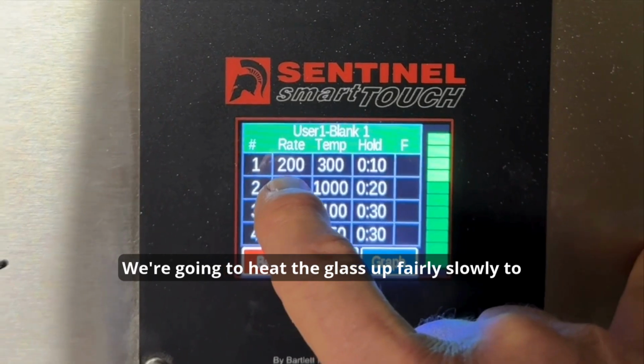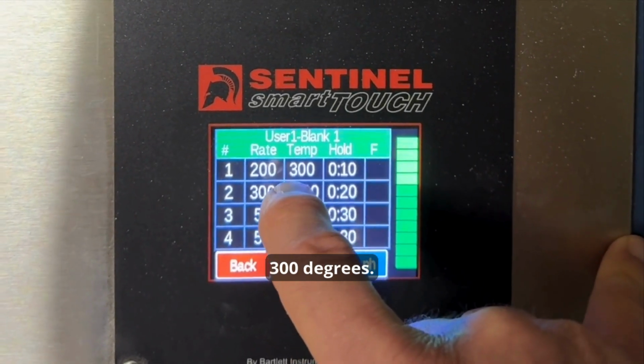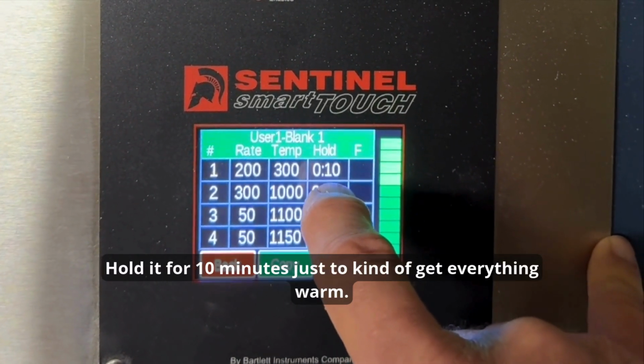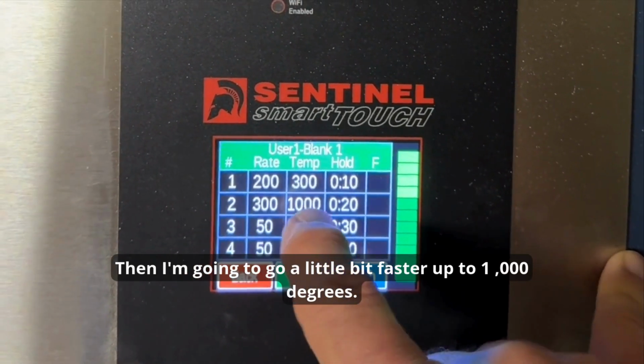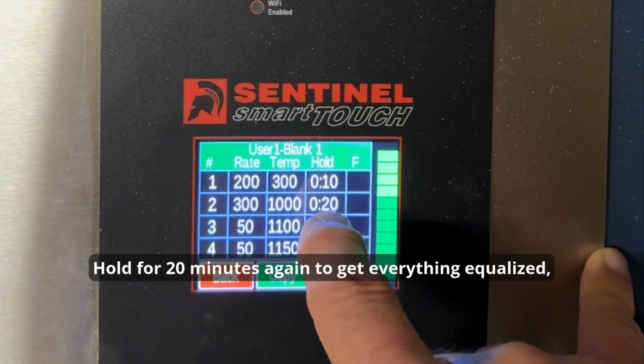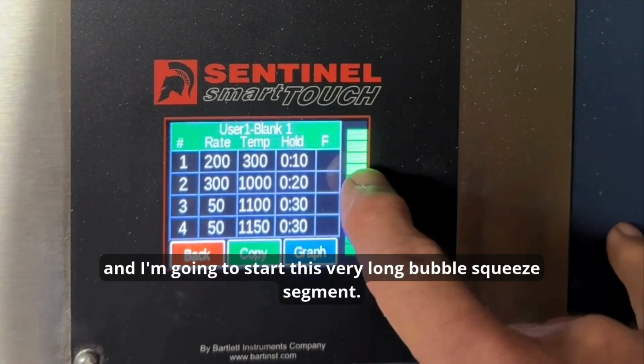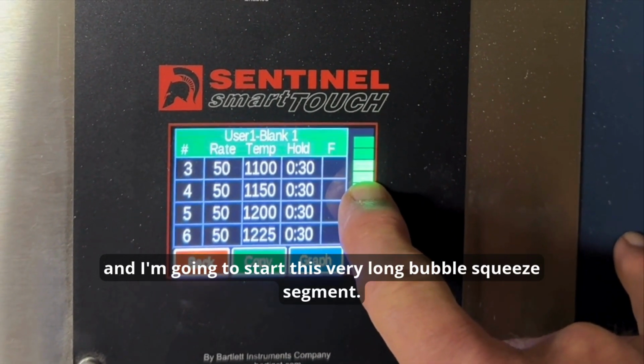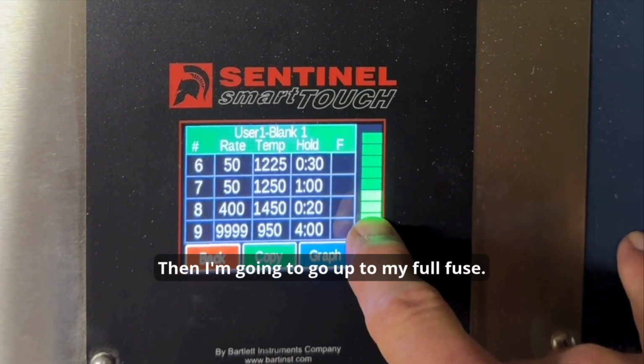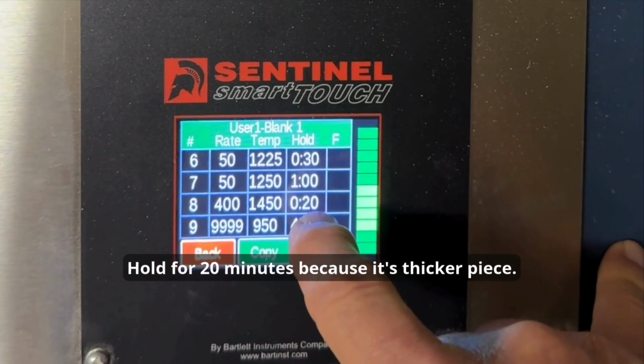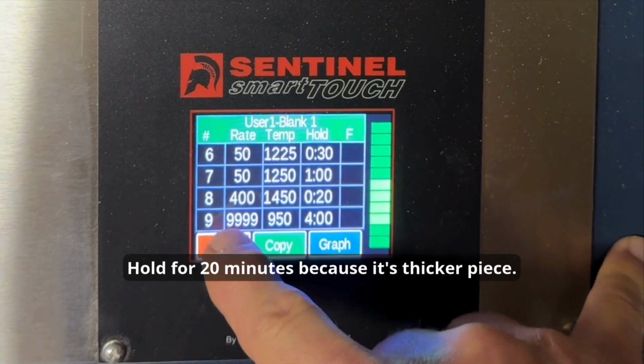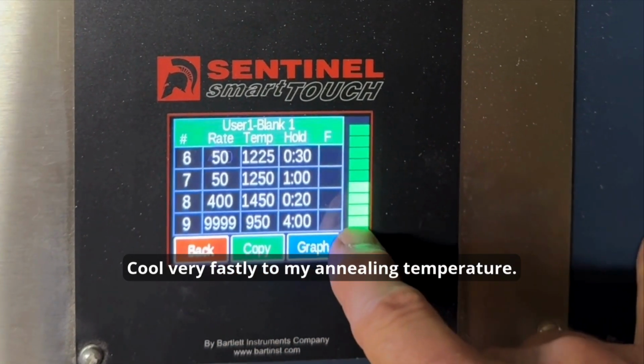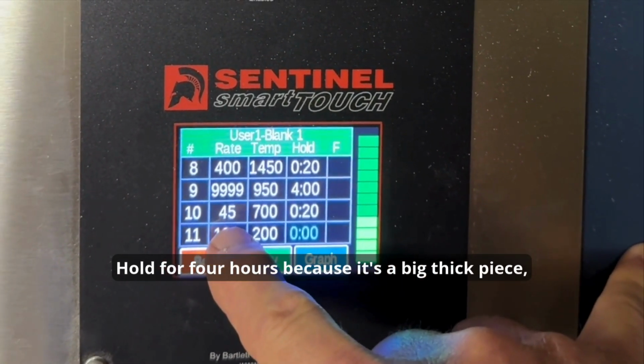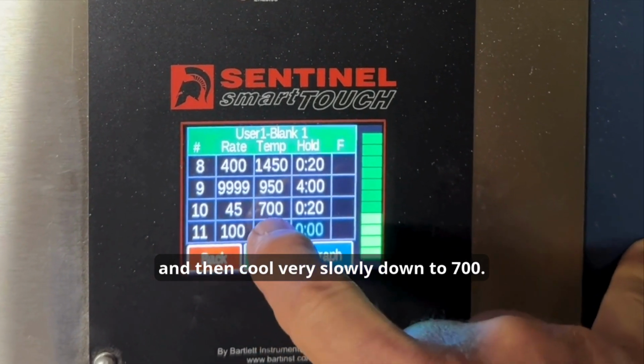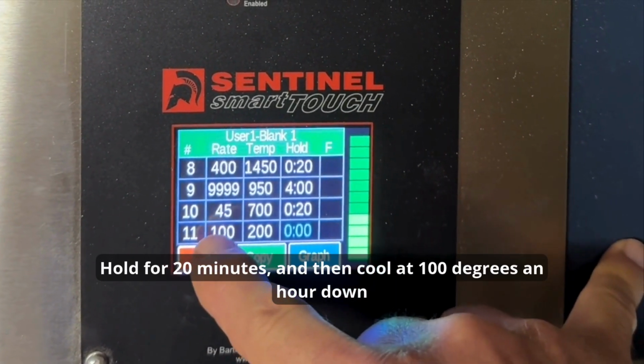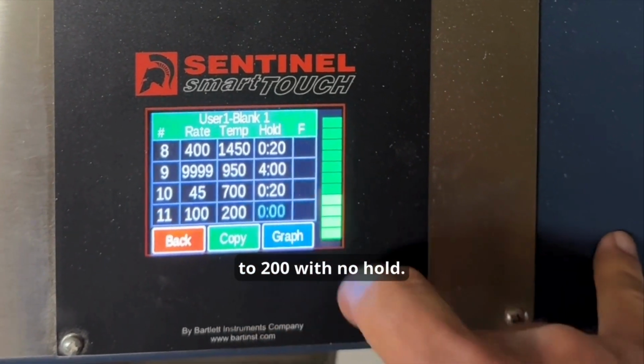We're going to heat the glass up fairly slowly to 300 degrees, hold it for 10 minutes just to kind of get everything warm. Then I'm going to go a little bit faster up to 1,000 degrees, hold for 20 minutes again to get everything equalized. Then I'm going to start this very long bubble squeeze segment. Then I'm going to go up to my full fuse, hold for 20 minutes because it's a thicker piece. Cool very fast to my annealing temperature, hold for 4 hours because it's a big, thick piece. And then cool very slowly down to 700, hold for 20 minutes, and then cool at 100 degrees an hour down to 200 with no hold.